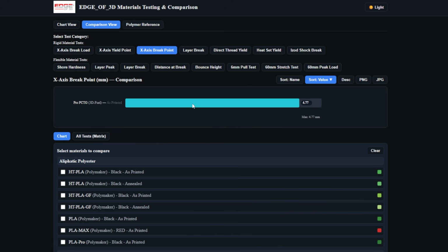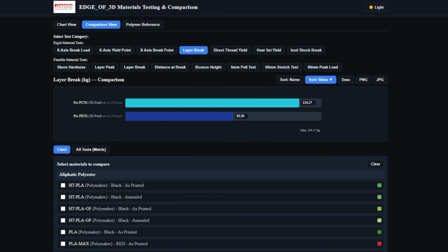The only break I had was one piece of the PCTG and it broke at 4.77 millimeters. Now, here's where the PCTG starts to shine. Layer adhesion. 134.17 kilograms versus 83.3. That's a 60%. Even though they broke funny and can't explain the reason for the breaks, where they broke at, especially on the PETG, that's still a 60% increase in strength over the PETG. So that's where the PCTG really starts to shine. And as you've seen in the heat testing, it's good about 10 degrees warmer as well. Direct threads, PCTG again 65 versus 54.95 for the PETG.